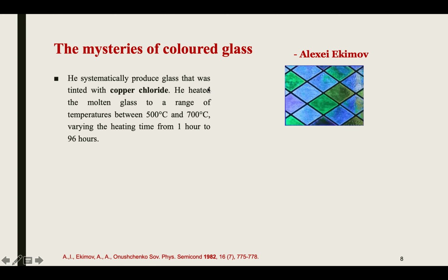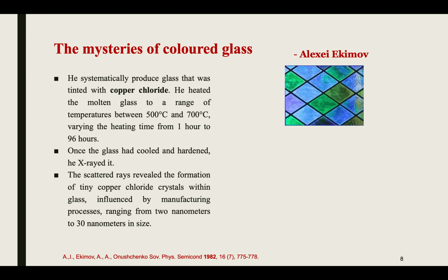So what he did was heat the molten glass, normal colorless glass, to a temperature between 500 degrees Celsius and 700 degrees Celsius. Within this range, he kept the glass at the temperature for different durations, from 1 hour to 96 hours. Then once the glass had cooled and hardened, he x-rayed it. What he observed in the X-ray was that the scattered rays revealed the formation of tiny copper chloride crystals within the glass, influenced by the manufacturing process, ranging from 2 nanometers to 30 nanometers in size.